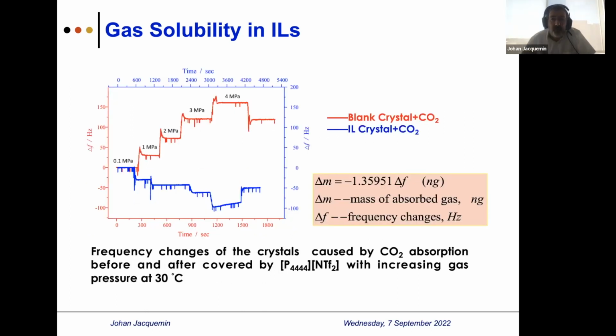I had a chance to use one, and I'm not a big fan of these techniques, but I had a chance, with a student from China, to use such a system for ionic liquids. And just to tell you, we start with a blank crystal, and we add the gas, and we record over time applying different pressures. We record the frequencies, and we do the same type of measurement by putting in a sample and measuring CO2.